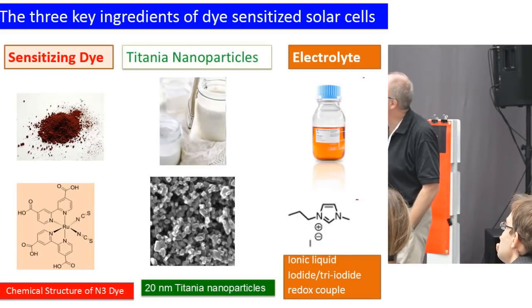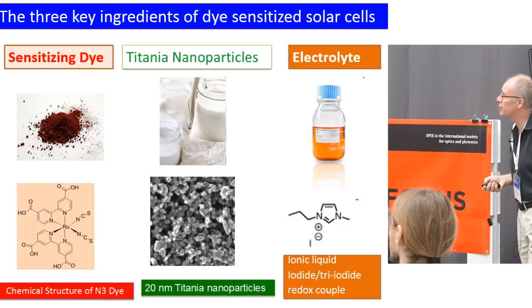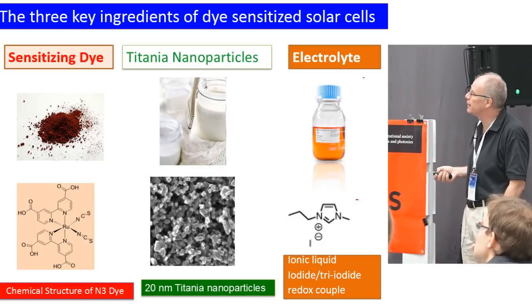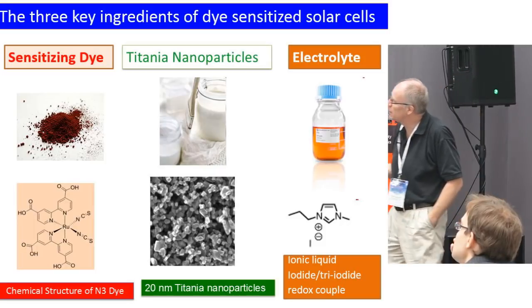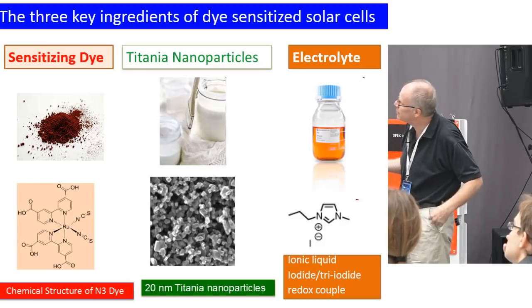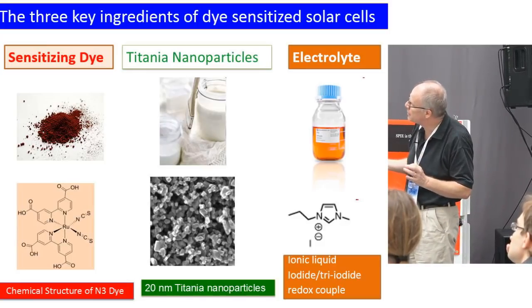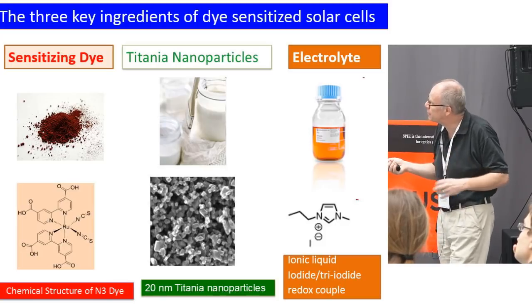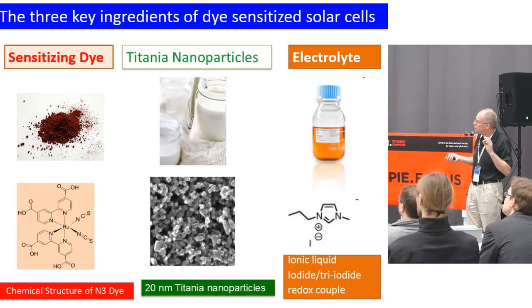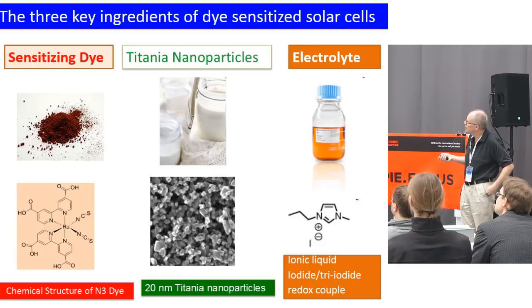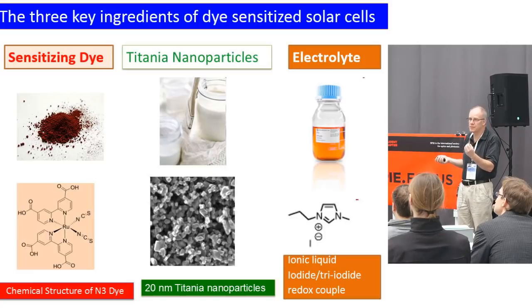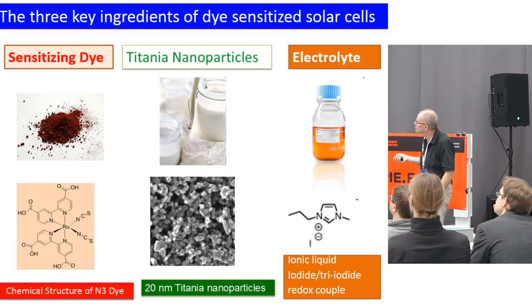These are the typical ingredients of a dye-sensitized cell from the starting point. This is from the early 1990s. This is what we can call a nano sponge in a way. It's 20 nanometer sized TiO2 particles. Its porosity is 50–60%, being porous all the way down to the contact. So it's a high surface area electrode, and one monolayer of dye now can absorb 100% of the visible light at the absorption maximum. So now we can take care of all the sunlight absorption.